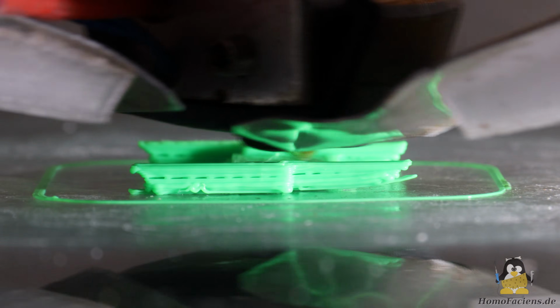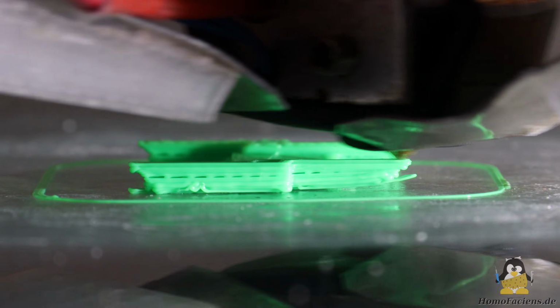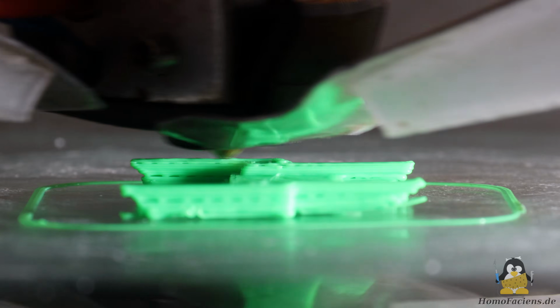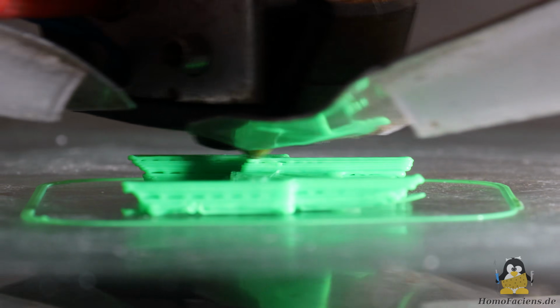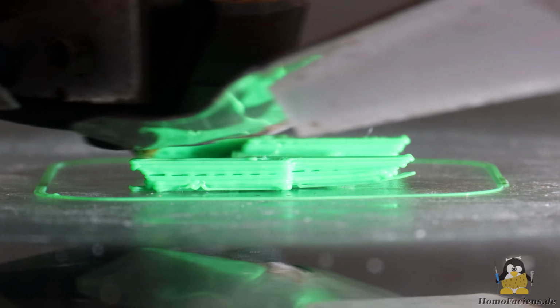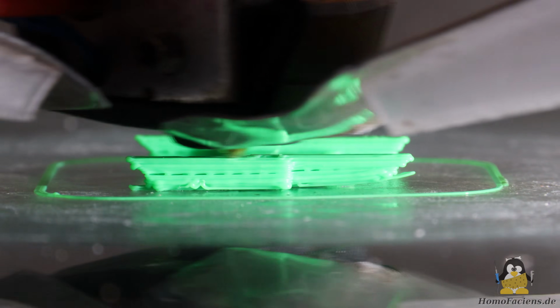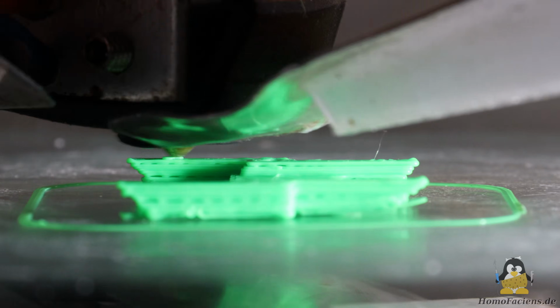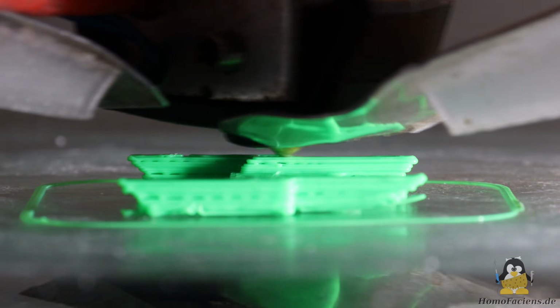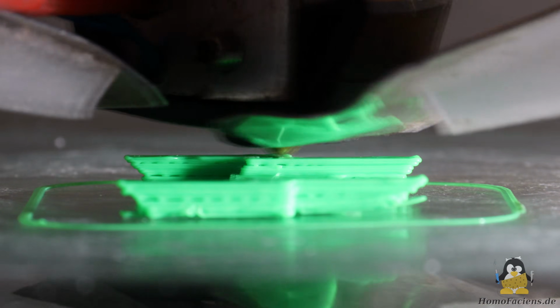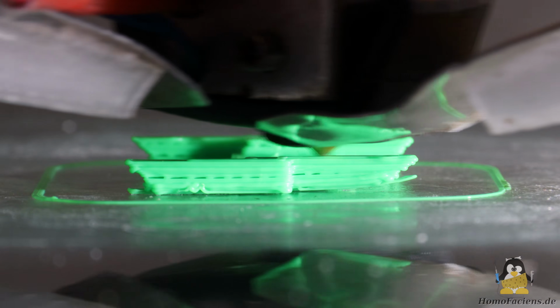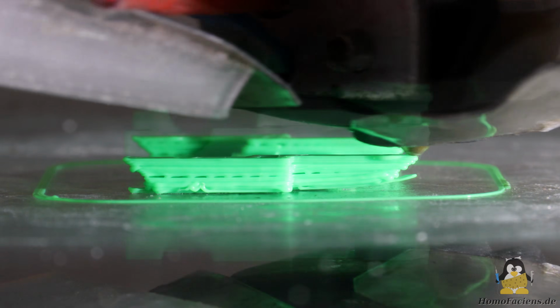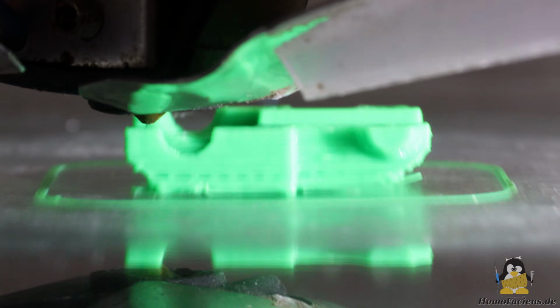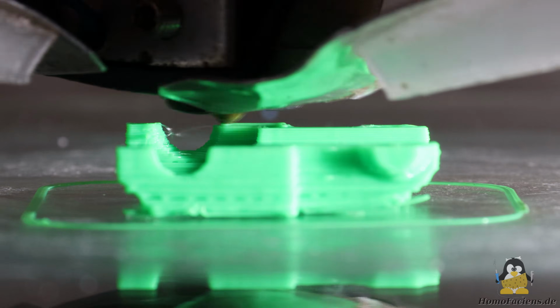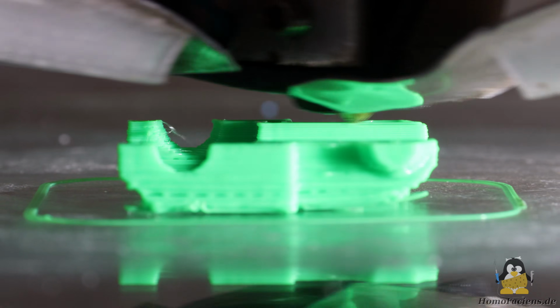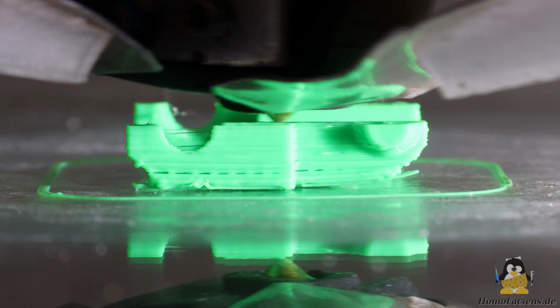So, what kind of print results can be achieved with the materials in my Extruder 7.2? First I loaded the pellets into the hopper. Extrusion works in principle, but it is anything but uniform. In addition to the aforementioned pellet size relative to the extruder volume, another material property is responsible for the poor print quality. To print with the pellets I had to increase the filament factor, which determines the amount of plastic extruded per screw rotation, to 3 times the value used for the recycled powder. A reduction was to be expected due to the difference in density.